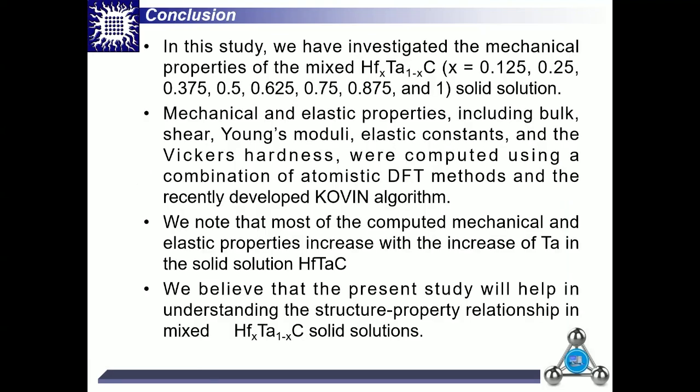Okay, to conclude, we have calculated all of these hafnium tantalum carbide solid solutions. We have investigated different elastic moduli and elastic constants, and this was computed with DFT methods and the new KOVIN algorithm. We note that there is a trend: the increase of tantalum gives an increase of the elastic properties within the solid solution, and we believe that this study is very important to understand the structure-property relationship in hafnium tantalum solutions.